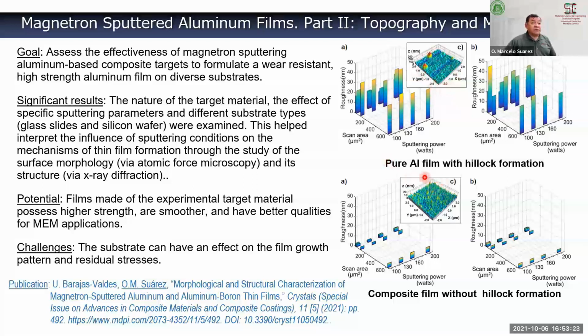But on the other side, when we tried our composite film, look at the scales: this is 300 nanometers, this is just 20 nanometers. So it may look rougher, but it's not. Actually the roughness is really small. So no hillock formation and low roughness. And we published this research this year, in 2021.